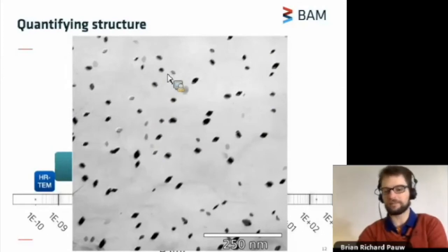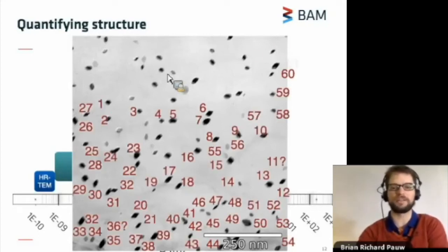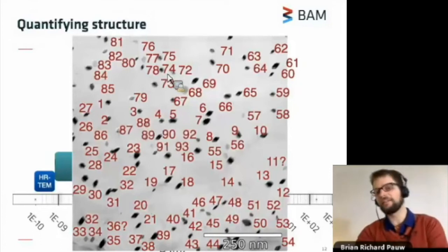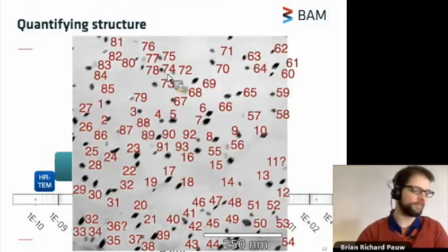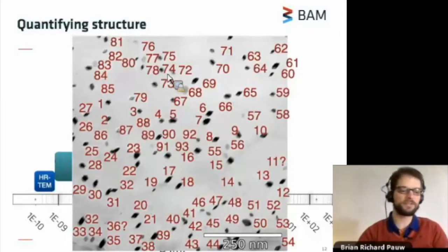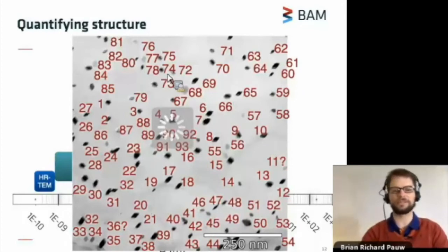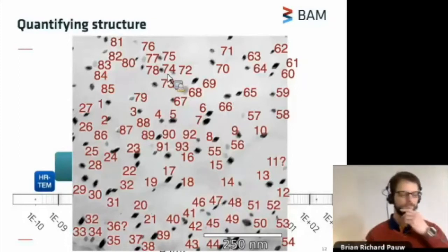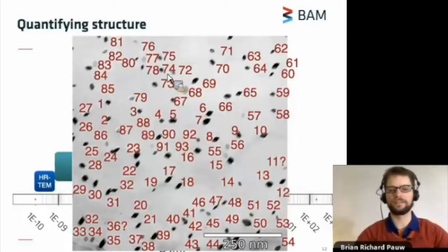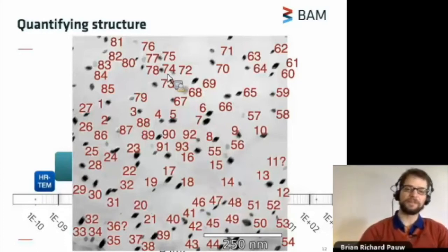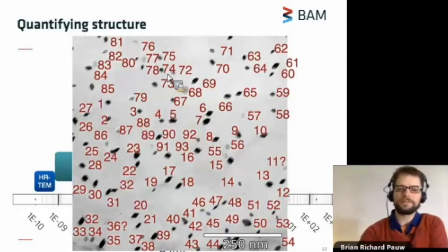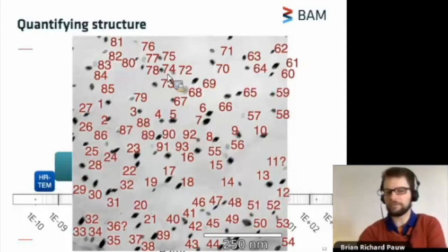If automated methods fail, you will be left to manually count and measure all of these structural details in your sample, which can be a very, very tedious task, and it introduces a risk of bias. Recent research has shown that if you want any sort of statistics from electron microscopy, you need to count at least 500 or even 1,000 precipitates or structural details at different magnifications, just to avoid this kind of bias. So that can be very tedious. And in the end, once you're finished with this, you will have quantified only a microscopic volume of material.